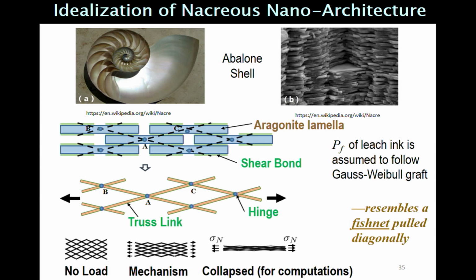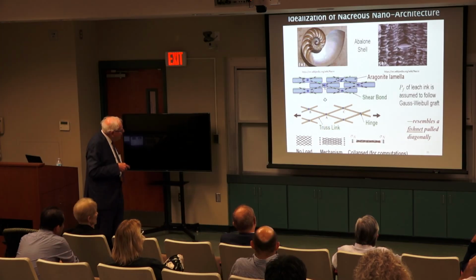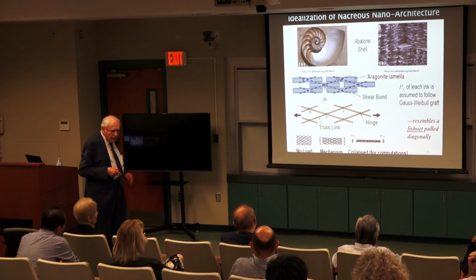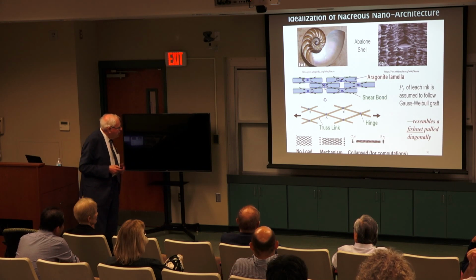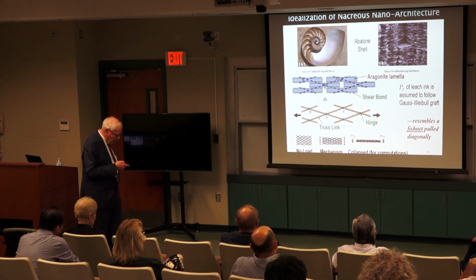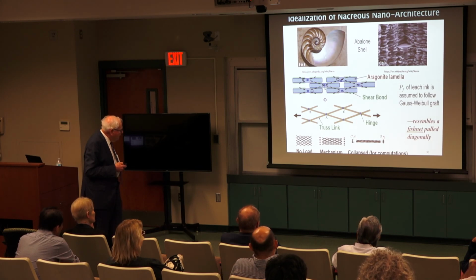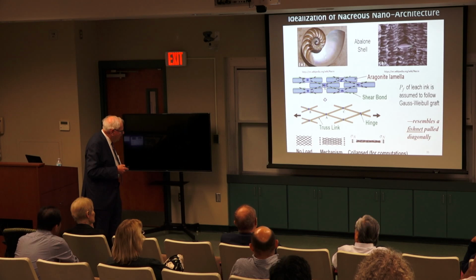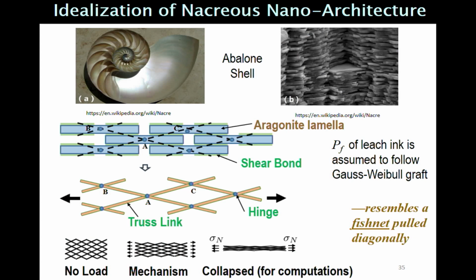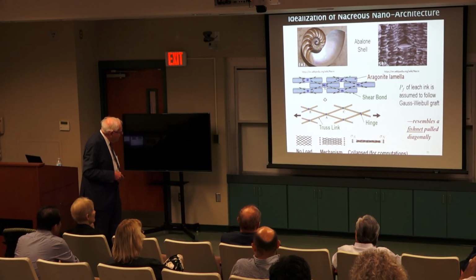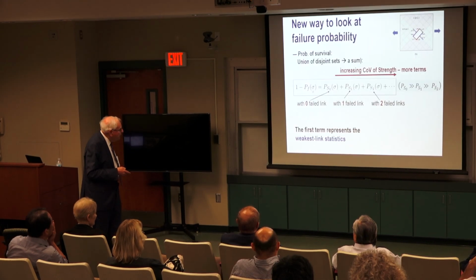So we have rigid elements, and under longitudinal loading, which is what is of interest here, not transverse loading, you have to transmit the force by shear from this platelet to this platelet, and then to this. So the force transmission looks like this, and it looks like a fishnet pulled diagonally. Okay. Now the question is, it can be solved, and it can also be easily simulated. My student runs millions of simulations. We actually use MATLAB, we use the program for a truss. Initially we propped it so it does not collapse, but it makes no difference statistically. We let it collapse to a line, but this connectivity is there, and that's how we obtain the results.